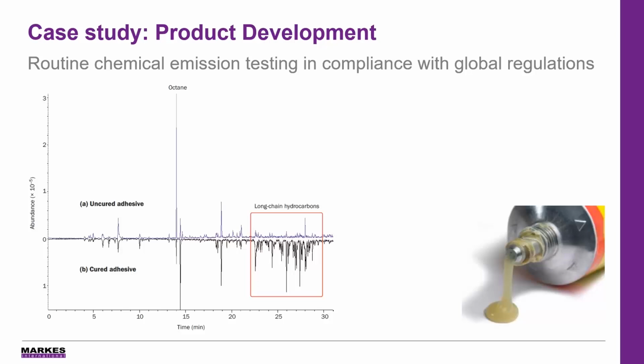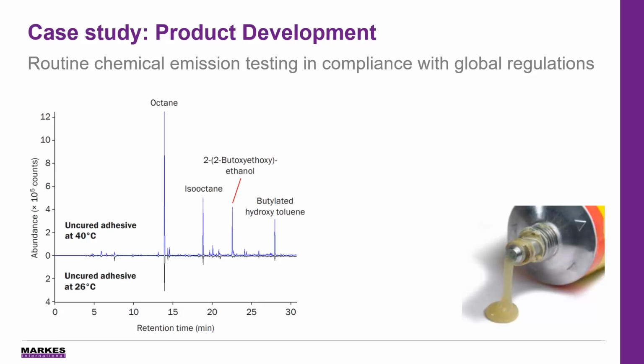Here you can see the comparison of the uncured adhesive at 26 degrees, which is that black trace on the bottom, with the uncured adhesive at 40 degrees. So again, just showing that big difference of emission range over that 14-degree difference.